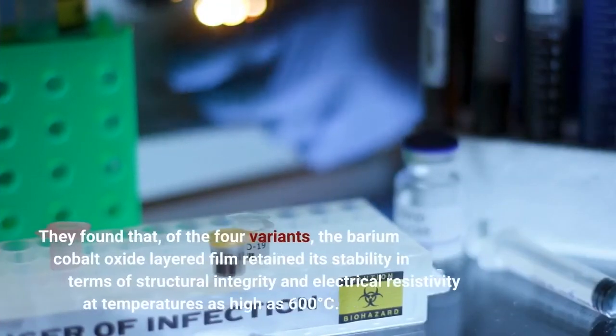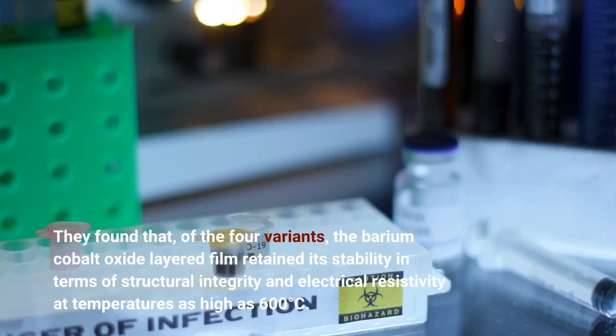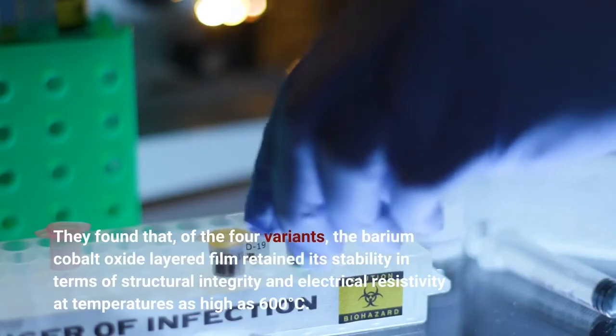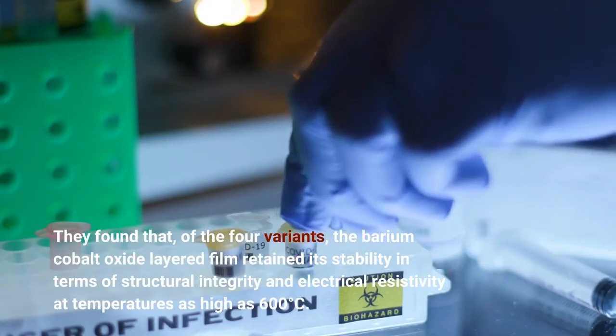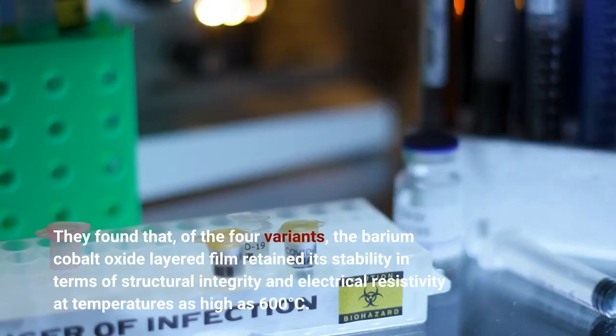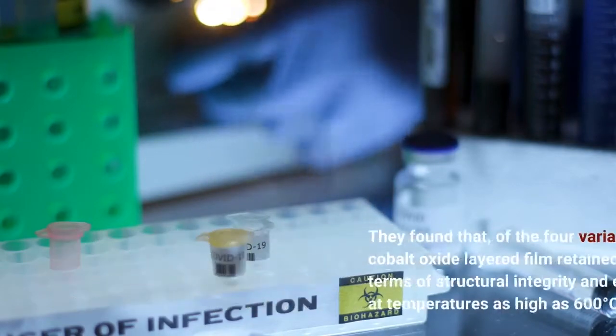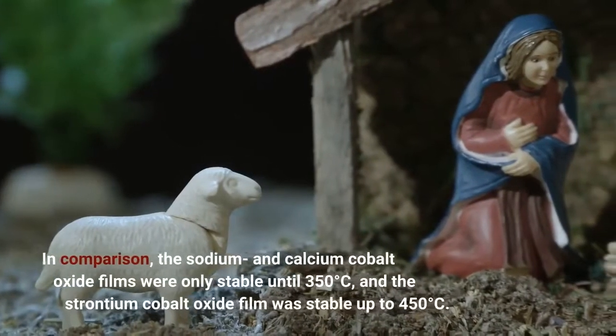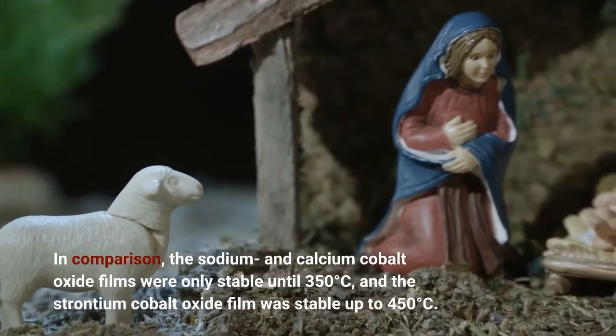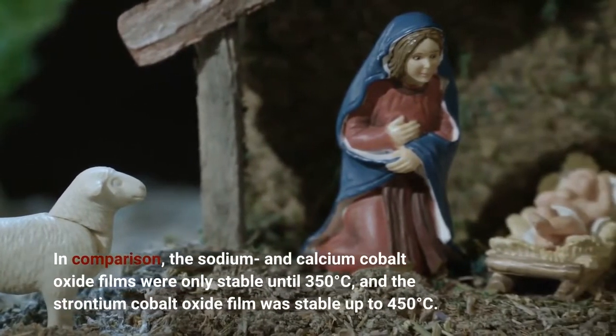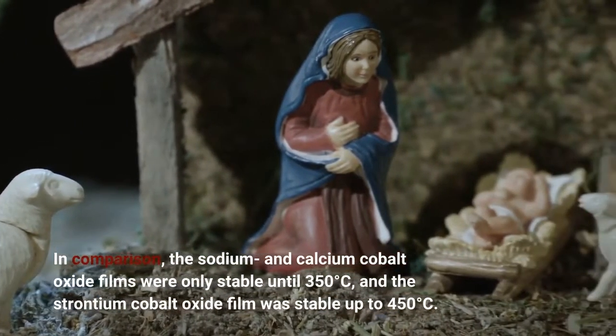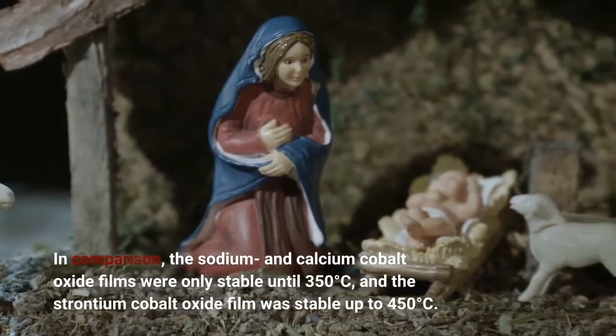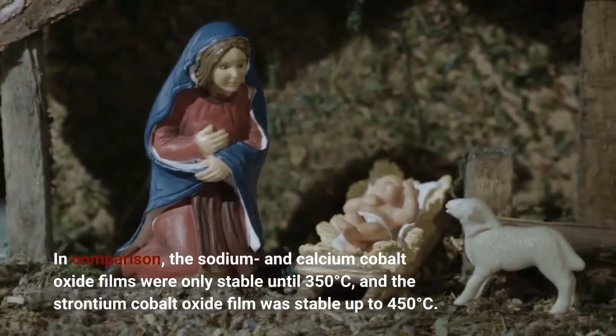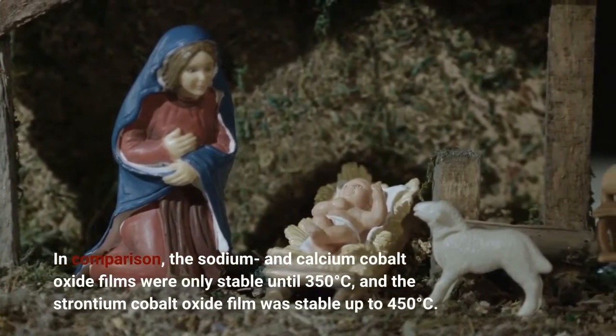They found that, of the four variants, the barium cobalt oxide layered film retained its stability in terms of structural integrity and electrical resistivity at temperatures as high as 600 degrees Celsius. In comparison, the sodium and calcium cobalt oxide films were only stable until 350 degrees Celsius, and the strontium cobalt oxide film was stable up to 450 degrees Celsius.